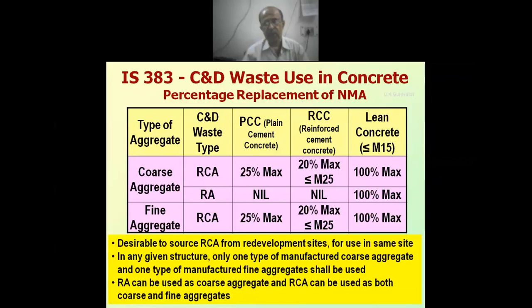Now coming to what IS 383 says with regard to percentage replacement of natural mineral aggregate. NMA is natural mineral aggregate. It says that it depends on the type of your concrete, whether you are using PCC, plain cement concrete, or RCC, or lean concrete, less than M15 grade. Lean concrete you use for the base course below the PQC. So C&D waste type RCA, recycled concrete aggregate, can be 25% maximum in PCC and 20% maximum in RCC. And in lean concrete, we can use 100%. RA is not advocated for either PCC or RCC, but in lean concrete, we can use it. As a fine aggregate, RCA percentage is 25, 20, and 100%.